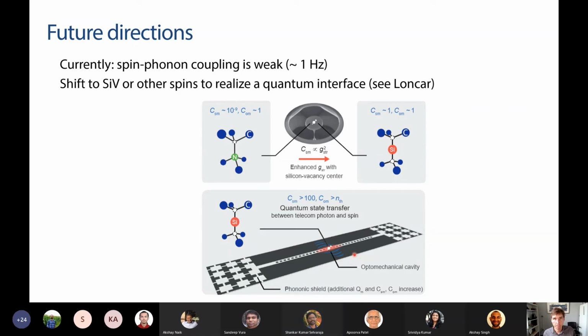I mean, for this specific experiment, the intrinsic stress didn't have a big effect. The static stress doesn't really affect your ground states, or it does, but not a huge amount. When you talk about optical excited states, intrinsic stress becomes very important. And if you go to silicon vacancies, it will also be important, where there's larger spin-phonon coupling. So in the short term, it hasn't been a problem. In the long term, it probably will be important.